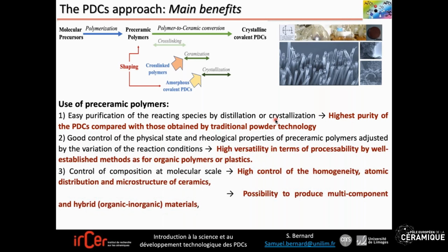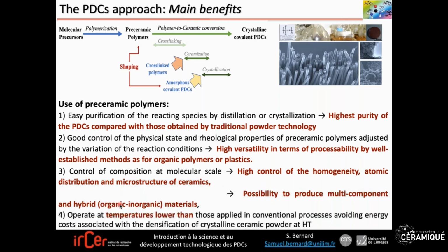So as I mentioned previously, you can control the composition of your ceramic at molecular scale because you start with a precursor. So it means you have a high control of the structural homogeneity and the compositional homogeneity of your materials. And you can produce a large range of ceramics from binary systems, silicon carbide, boron nitride, aluminum nitride, to multi-component materials made of 3, 4, or 5 elements. And you can also prepare hybrid materials. You mix your precursor with organic polymers, for example. And at the end, I will say that in general, you operate at temperatures lower than those applied in conventional processing. For example, you can prepare silicon carbide at 1000 degrees C from a polymer. It will be amorphous. If you want to crystallize, you can reach a temperature of 1500 degrees C or 1800 degrees C, but this is still lower than the conventional process to prepare silicon carbide.